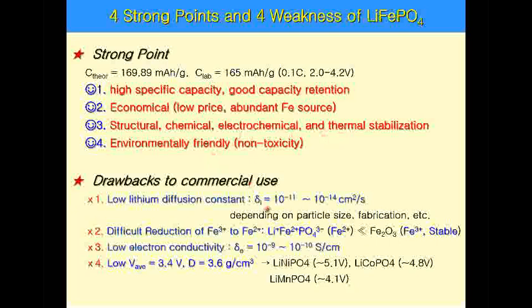However, several critical drawbacks will be the greatest hurdle to commercial use. First, it contains a low lithium diffusion constant. And especially when the active material contains Fe ions, one must prevent formation of Fe3+, because it is very difficult to reduce from Fe3+ to Fe2+. Another drawback is patent issues. If we can solve these problems, we can consider LFP as a good candidate for commercial use because of its superior structural stability.